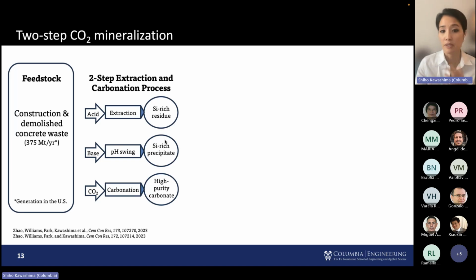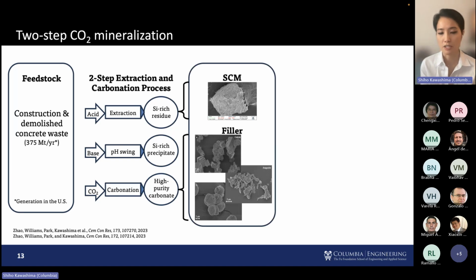Volumetrically, it's much less than the residue, but that also has some silica, so a potential candidate as an SCM. And then finally, from this two-step process or the pH swing, you've removed most of the impurities, and you're left with calcium. Then you apply the carbonation, and you can produce high purity carbonates. So in this two-step extraction and carbonation process, you end up with two products. One is a silica-rich material, and that can serve as an SCM. The other is a high purity carbonate, which can serve as a filler. And importantly, by tailoring the parameters of the process, you can produce different polymorphs with very distinct morphologies, and that can lead to different functionalities when you introduce it into cement.